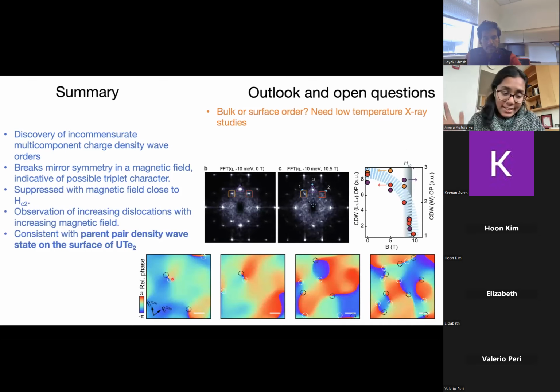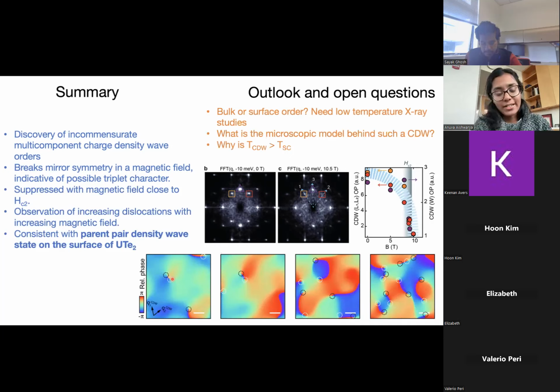One is, because STM is extremely sensitive to the surface, is this a bulk order or a surface order? This needs low temperature X-ray measurements, which are non-trivial because the CDW has a very low TC. Then, what is the microscopic model behind such a CDW? And the final question is, why is the temperature of the CDW melting higher than the temperature of superconductivity reported in UTe2? I think these are areas of active research at the moment, but there are no clear answers at this point.